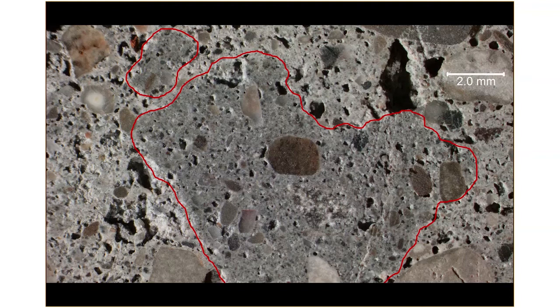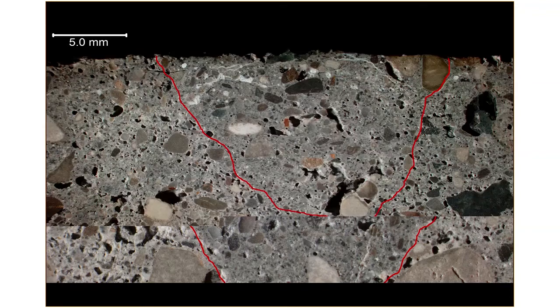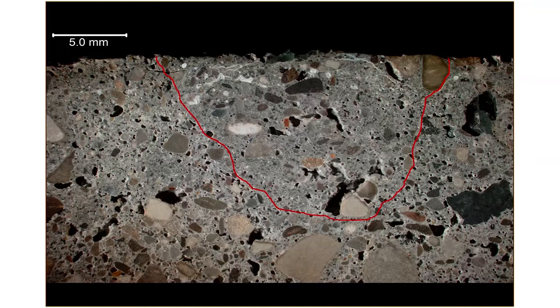So hand mixed, and so we don't expect the greatest mixing. And we got these areas that were a little bit denser and undermixed, and so all in all, they did a great job. But we can certainly find these anomalies. Here's another anomaly outlined in red of darker, denser concrete, had less air bubbles in it, and just part of the mixing process. And note that cracking up towards the top surface. There's some white secondary deposits, and there's some cracks that are very white and filled with secondary material. So very interesting there. We'll see some closer views of that.